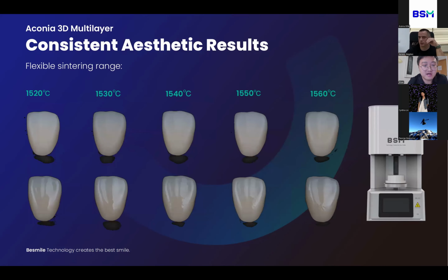The new multilayer has a flexible sintering range from 1520 to 1560 degrees. Within this range, it can give you stable, reliable outcomes every time. So for example, you can see here are the sintering results, 5 crowns sintering results at different temperatures: 1520, 30, 40, 50, and 60 degrees.